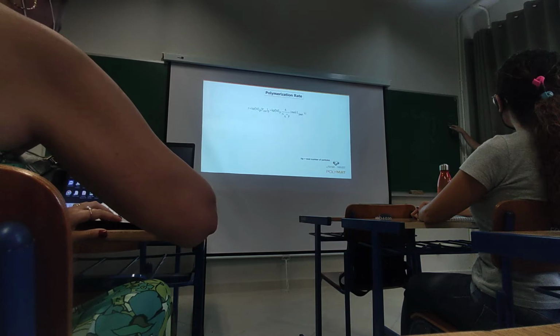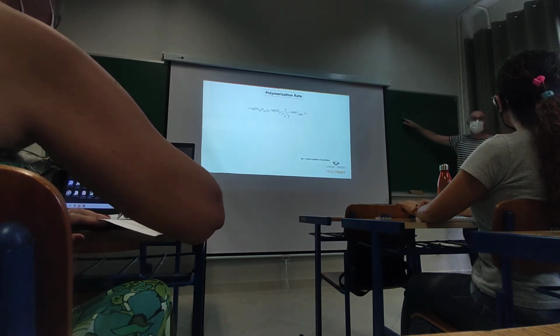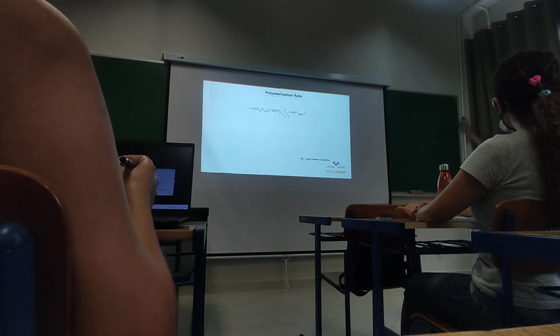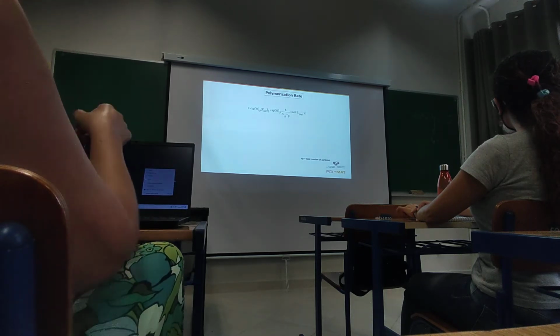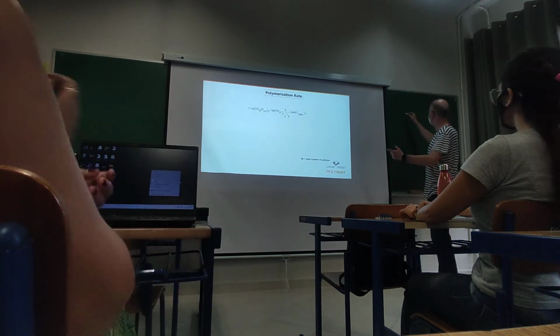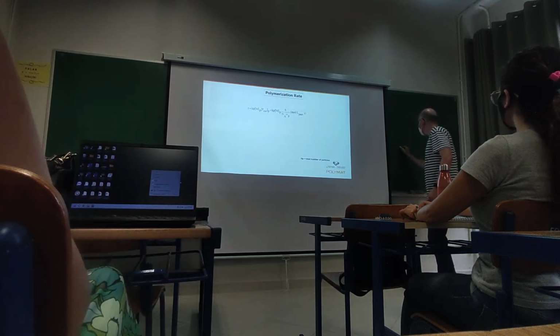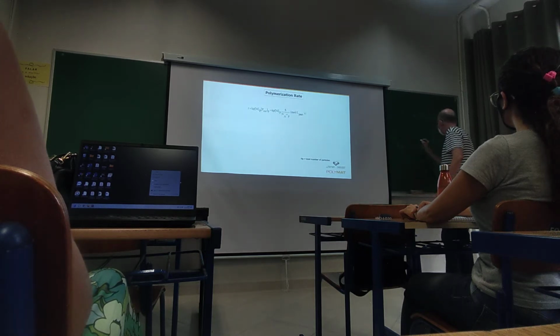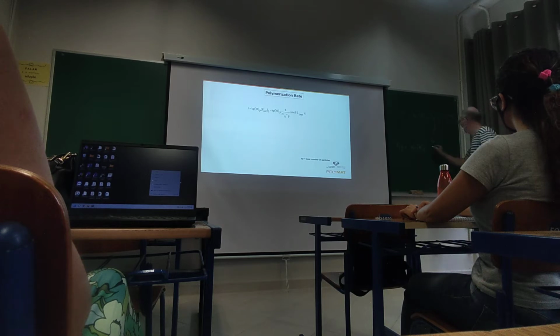If you want to calculate the rate of polymerization per particle, we have to multiply this by the volume of a particle. Okay? So that the expression, okay, this is the rate of, I use R, yes. So the rate of polymerization per particle will be Kp, monomer concentration in the polymer particles, and n bar.